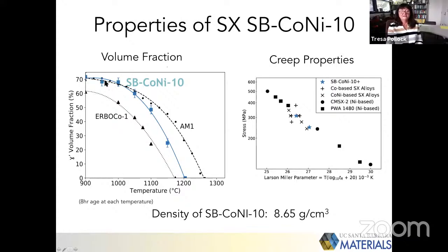And we have a high volume fraction of precipitates up to 1200 C. So this means the solvus of the material is at 1200 C. And I show this in comparison to a nickel-based single crystal superalloy. And so what you can see is that these alloys are similar in principle to superalloys that are currently flying in aircraft engines up to about 1100 C, and that they have a lower solvus compared to most nickel alloys. And this becomes very important to the printing process. They also have densities that are similar to existing nickel-based alloys.